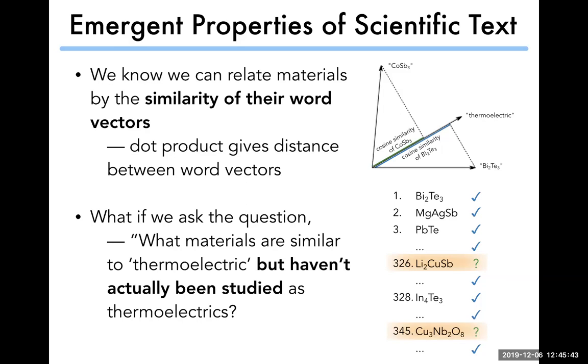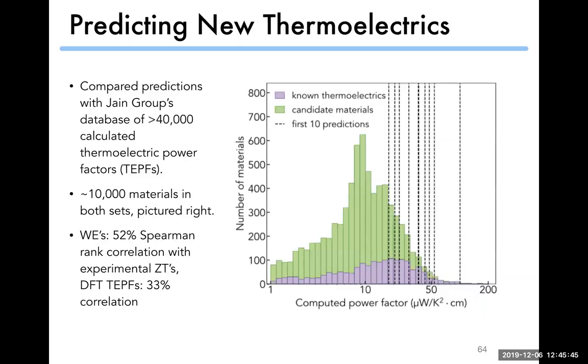So what we did is we took the top 10 or so suggestions in this ordering of the similarity with thermoelectric, and we plotted that against the thermoelectric power factors that the Jain group had calculated for a really large number, like 20,000, it looks like 40,000 materials. And then we also had a set of known thermoelectrics from that set. So we looked in the literature at what materials had been mentioned as thermoelectrics in our corpus.